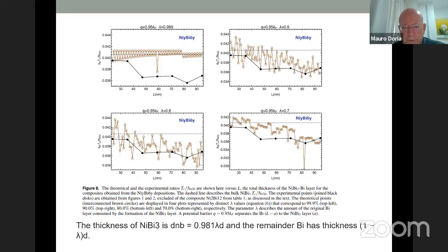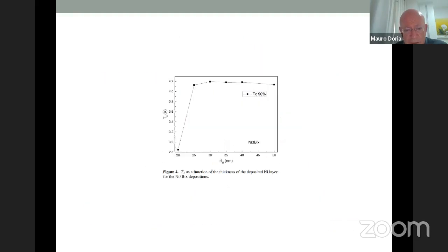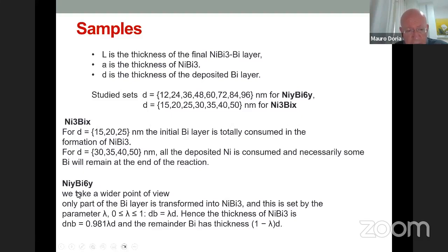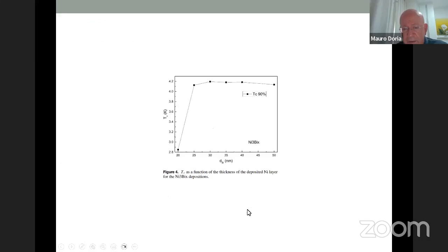So in conclusion, we cannot say that there is TC oscillation for sure. We say that our model is consistent with the possibility of the old Blatt and Thompson model. Perhaps I went too far because the time is running out. In this set of samples, we don't know if all the nickel is consumed, but we make the assumption that only part of the bismuth is transformed, according to some parameter lambda. This lambda sets the thickness of nickel bismuth and the remainder thickness of bismuth. So there are some assumptions here.